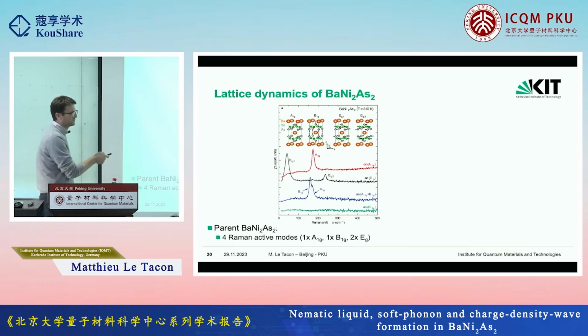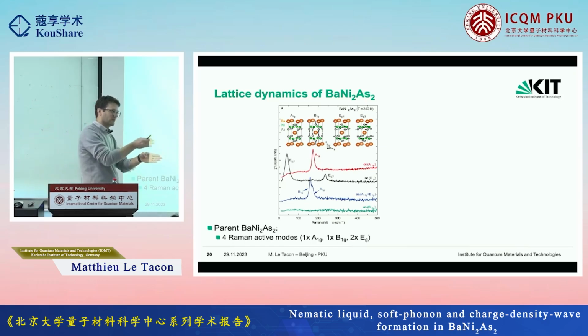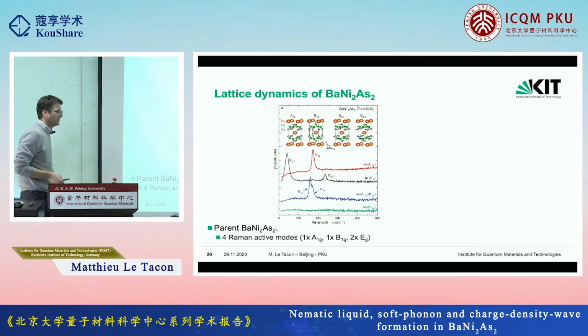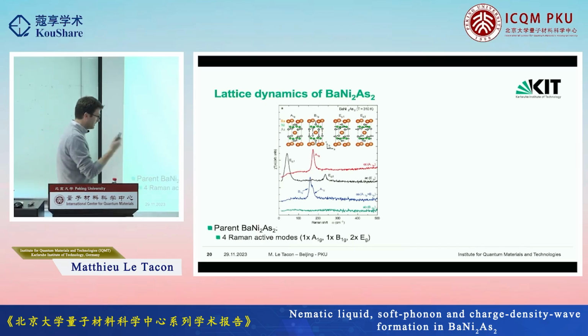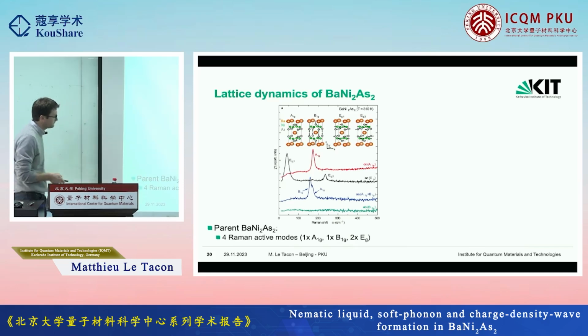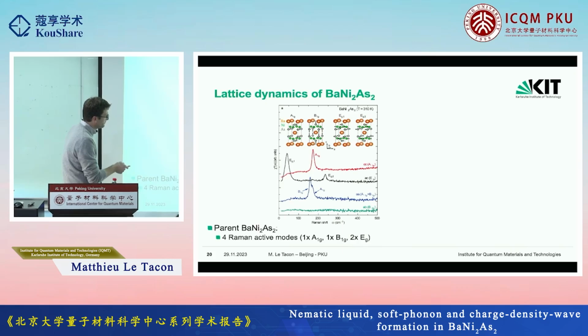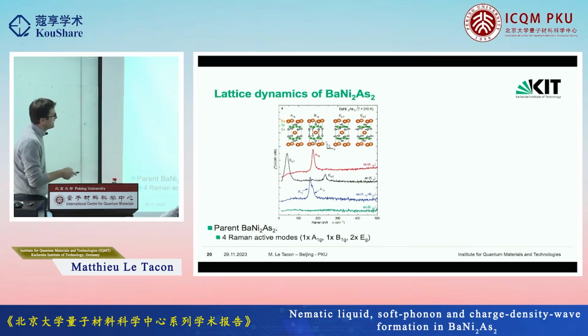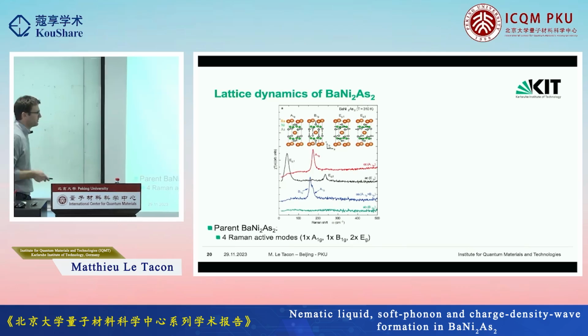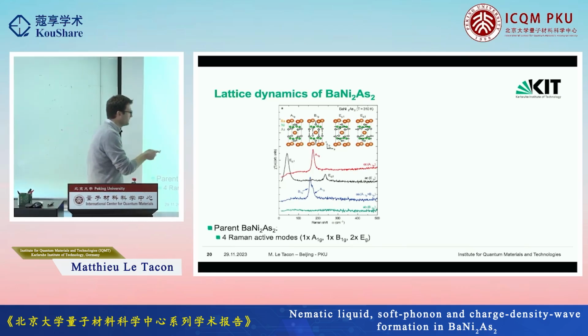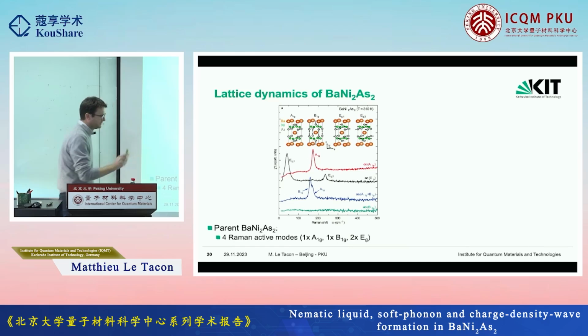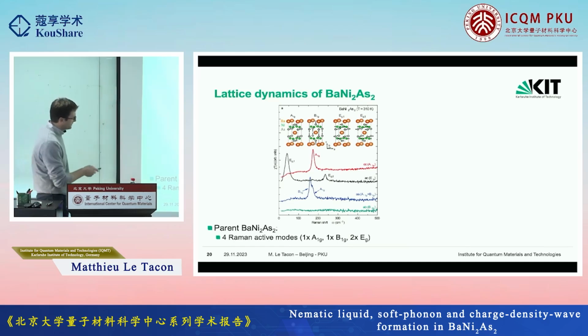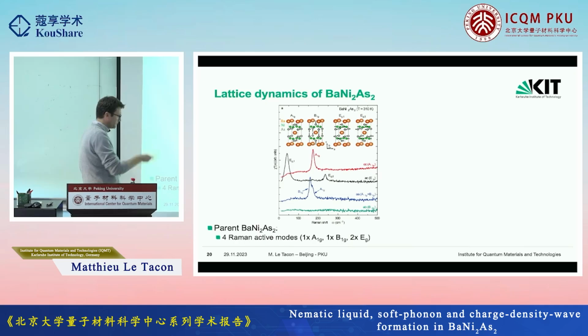So it's a lot of fun to measure the Eg mode because you have to put yourself on the side of the sample, and you need a very high spatial resolution, which is allowed by the micro-Raman spectrometer that we operate. But in short, that's how it looks. So you have the A1g mode, you get the B1g mode, so in that case you see both together. And if you get the cross-polarization on the side, you see nicely the 2 Eg phonons. There are a few things that are already remarkable. I mean, this Eg phonon is quite soft and it's quite broad. But for the moment, we just ignore this, and we cool the system down.